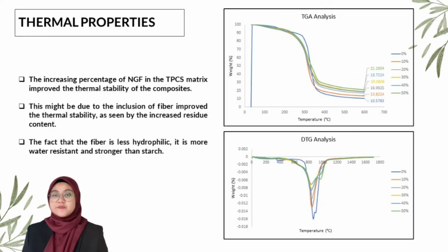In terms of thermal properties, the increasing percentage of Napier grass fiber in the TPCS matrix improved the thermal stability of the composites. This might be due to the inclusion of fiber improving the thermal stability, as seen by the increased residue content. Moreover, the fiber is more water resistant and stronger than starch.